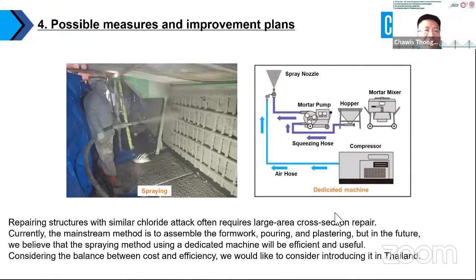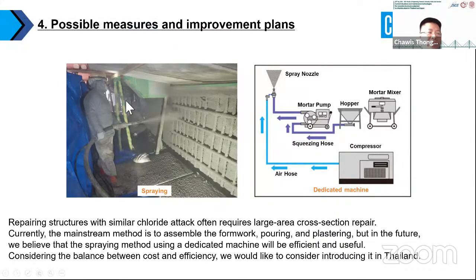The possible measure for the future case is the spraying method. With the spraying method in section repair work, a thickness of about 30 millimeters can be sprayed with one spray. Additionally, although it depends on the work condition, the amount of spraying per hour is about 0.2 cubic meters with our formworks. So the time efficiency is very high and the productivity is to be greatly improved.